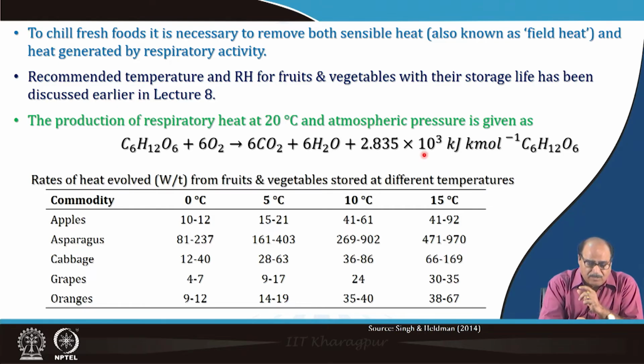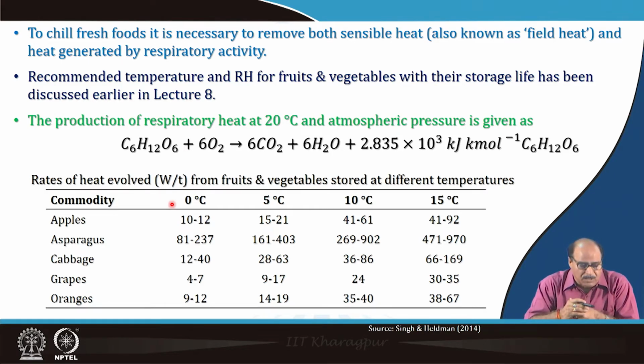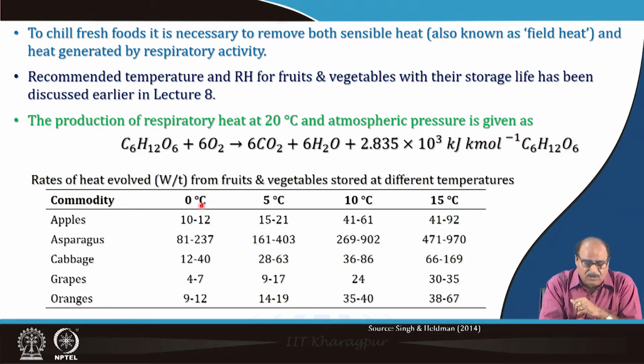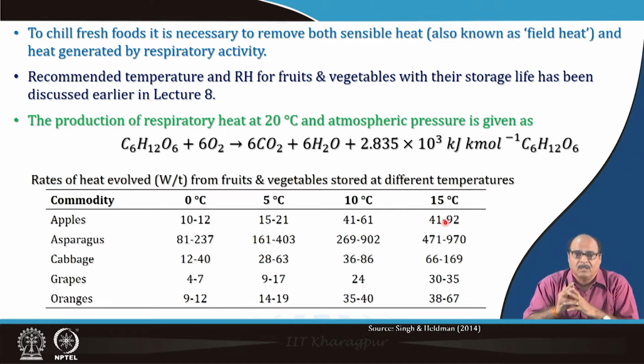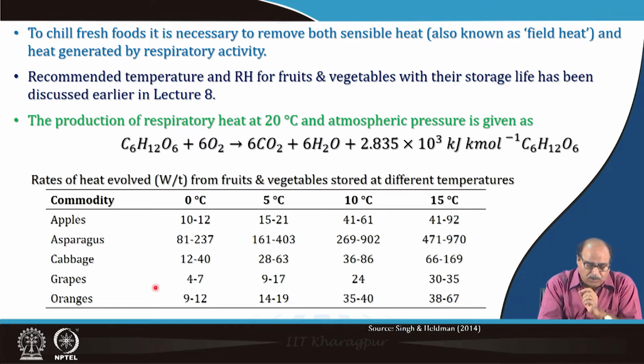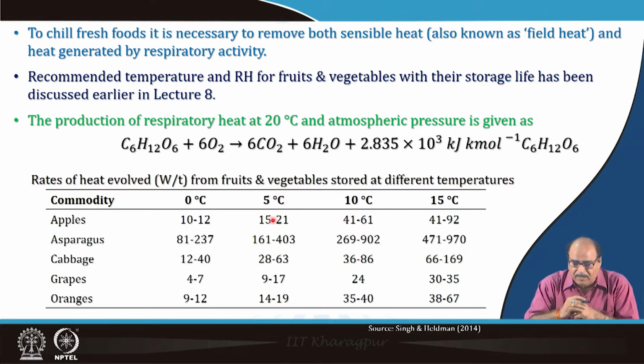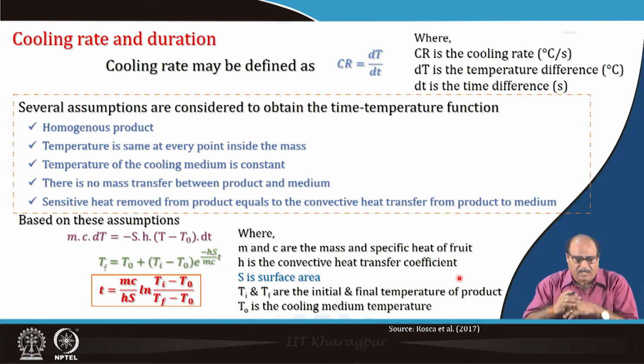In this table I have given the rates of heat evolved in watt per ton from the fruits and vegetables stored at different temperatures. For example, apples stored at 0 degrees Celsius may produce 10 to 12 watt per ton of heat, whereas the same apple at 15 degrees Celsius may produce 41 to 92 watts per ton. Grapes produce 4 to 7 watts per ton at 0 degrees Celsius, 9 to 17 watts per ton at 5 degrees Celsius, or 30 to 35 watts per ton at 15 degrees Celsius. So, these are the important commodities. The rate at which they evolve heat at different temperatures is shown, and this can be used for calculation of the refrigeration load etc.